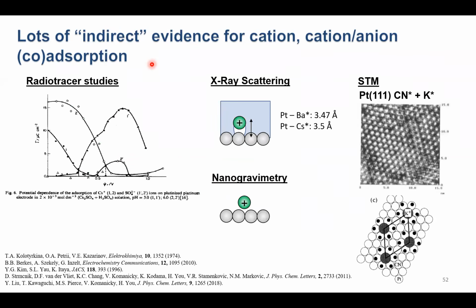So again, what we're saying here is that maybe we don't have significant electron transfer, and so we don't see it in the CV, but that doesn't mean the cation can't still sit close enough to the surface that it gives up some of its solvation. And I think there's lots of experimental evidence that indirectly supports this idea.